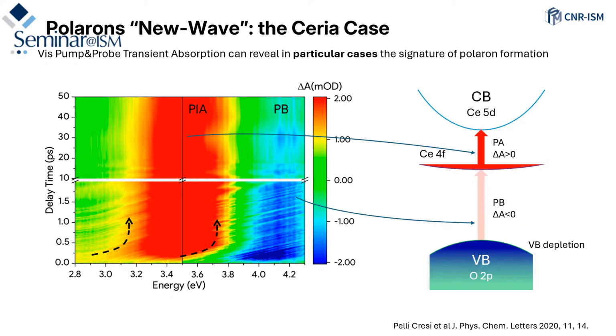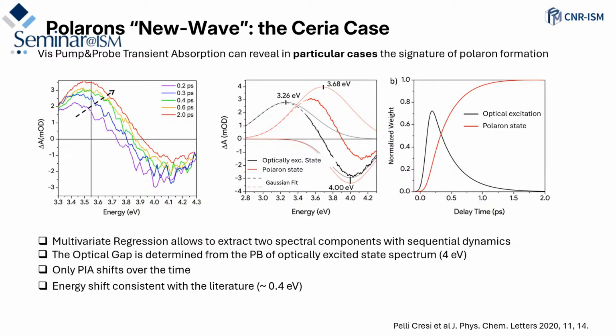And we have also the positive photoinduced absorption induced by the transition from the 4f state to the 5d. You can see also that we have this very fast shift in the transient absorption that we ascribe to the formation of polaron states, which are below the 4f state. And here is more clear the shift induced by the photoinduced absorption. From the map, we use multivariate regression just to extract the two spectral components. The first one is the optically excited state, and the other is the polaron state. We ascribe it to the polaron state.